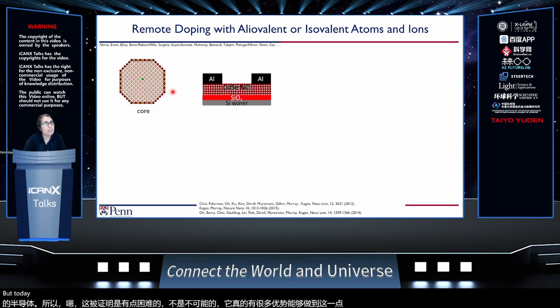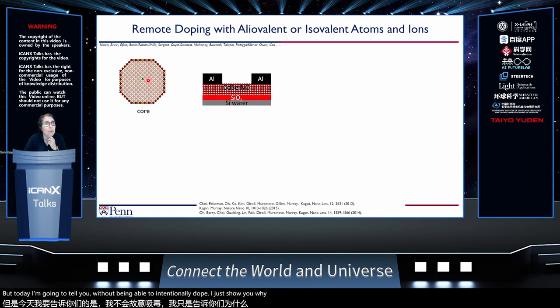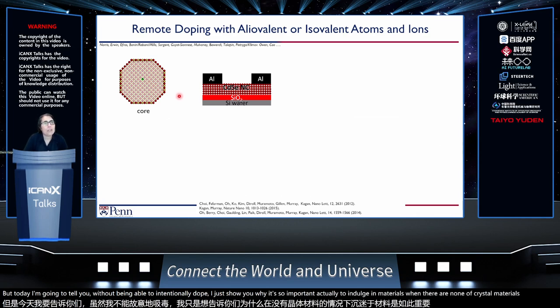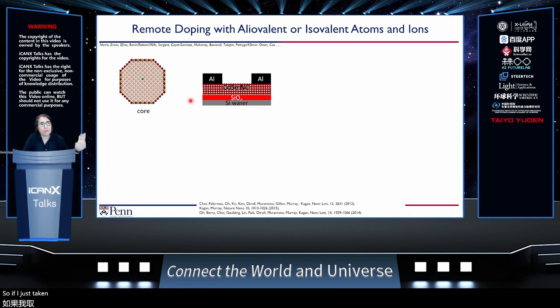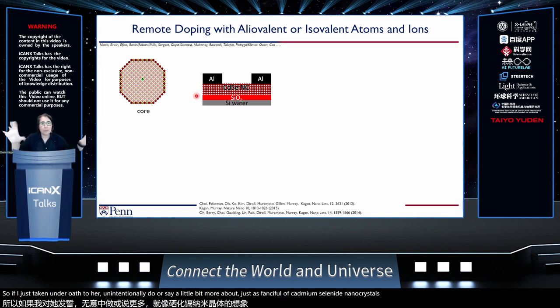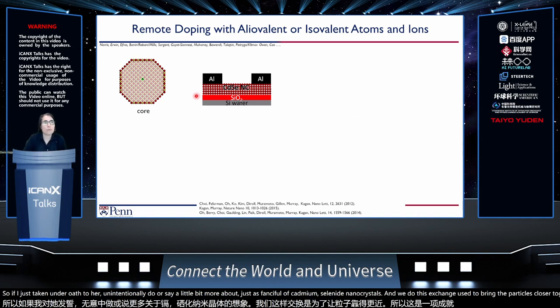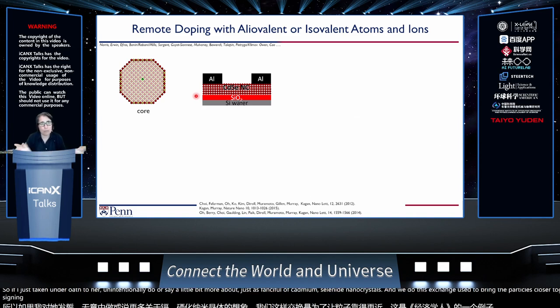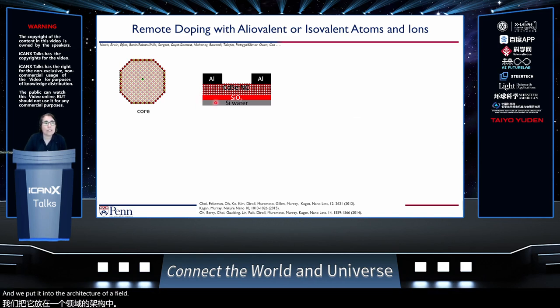But today I'm going to show you why it's so important to dope the materials when they're nanocrystalline, without being able to intentionally dope. If I just take an undoped or unintentionally doped sample of cadmium selenide nanocrystals, and we do this exchange to bring the particles closer together, I'm going to show you an example where we've used thiocyanate to bring the particles closer together. And we put it into the architecture of a field effect transistor. It allows us to study the transport characteristics.